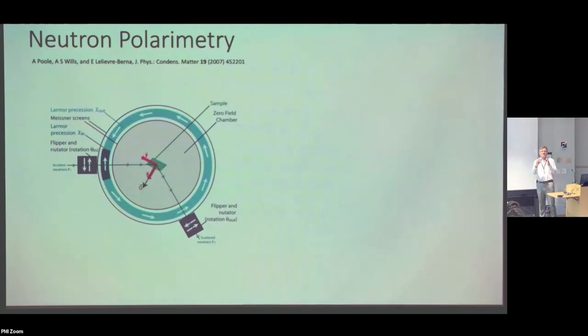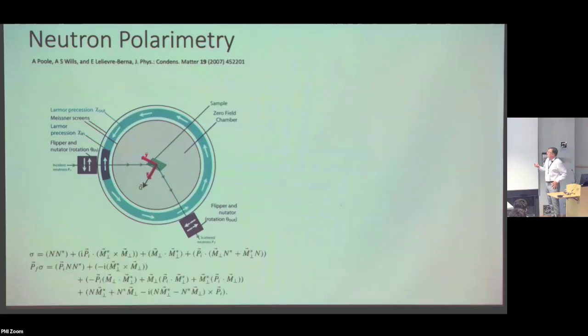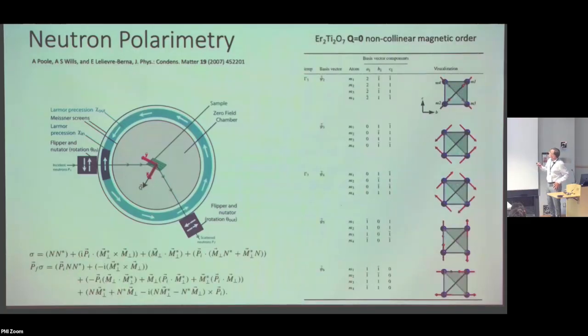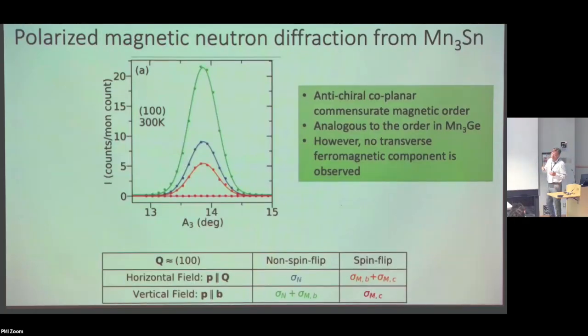So that gives you a whole matrix, like a rotation matrix for each Bragg peak. And that's a much more detailed kind of information. It's called neutron polarimetry. Very cool technique. And it's needed really for complex structures. In this case, manganese tin, we could use it to separate out the magnetic and the nuclear part of the diffraction cross-section. So here's an experiment on the 100 diffraction peak in manganese tin. And I am showing you